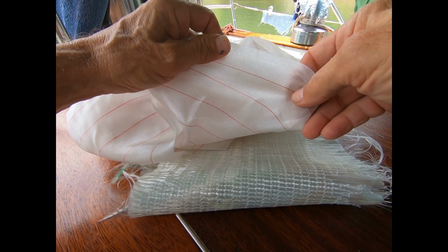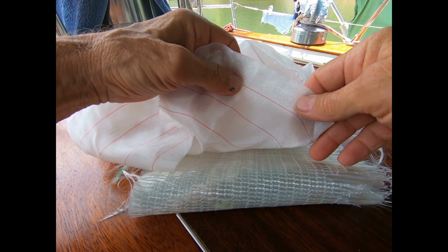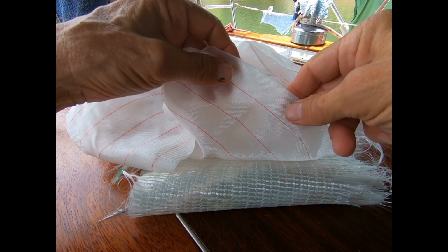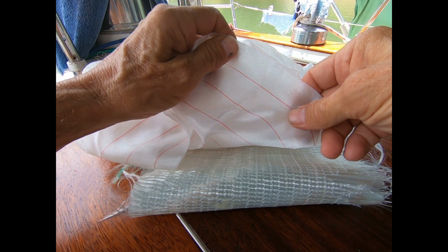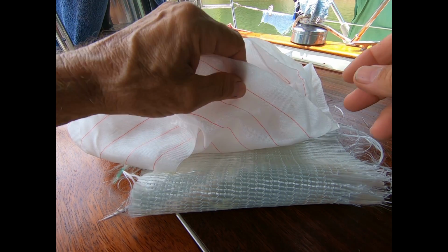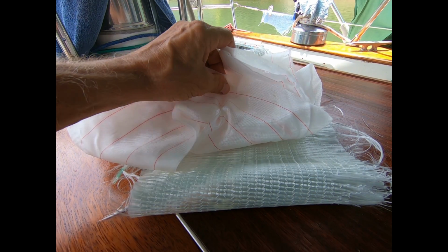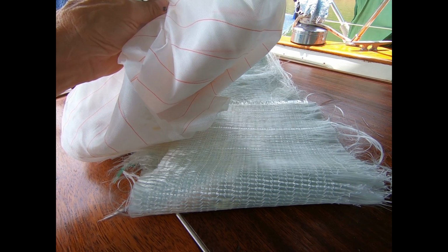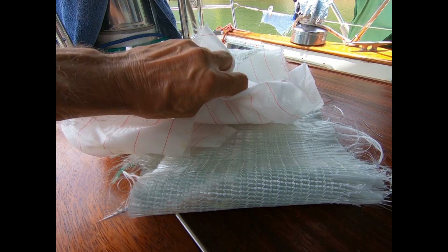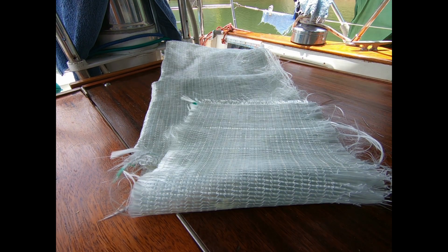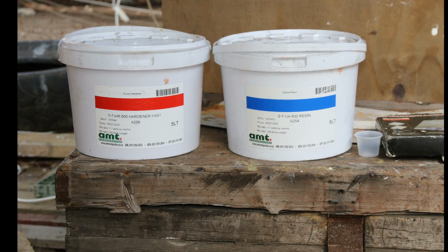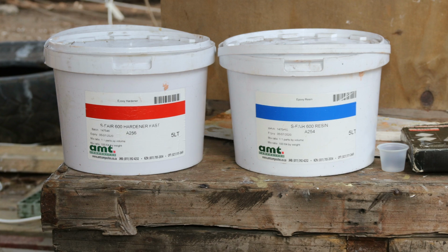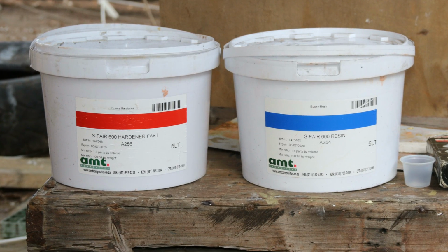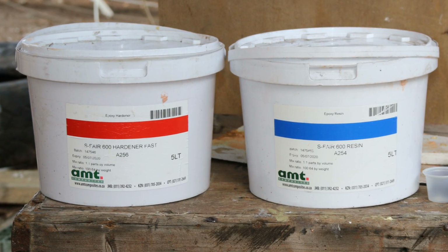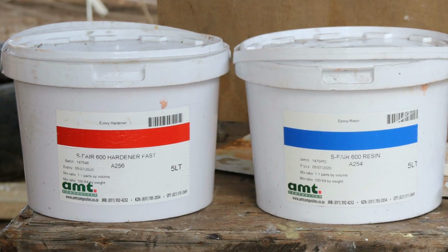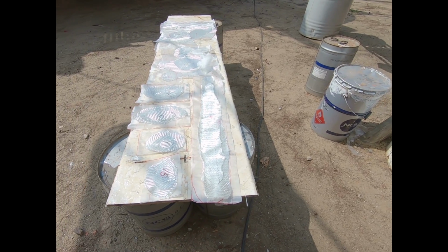And along with using the peel ply, any amine blush, which is a chemical reaction in epoxy resins, comes off in the peel ply, so there's no more washing or any other prep work that's needed on our laminate, on our layup, after the peel ply comes off. Actually, amine blush is a reaction between the epoxy hardener and the surrounding humidity in the atmosphere. Some hardeners, like what's used in 2-part epoxy putties, don't create amine blush.